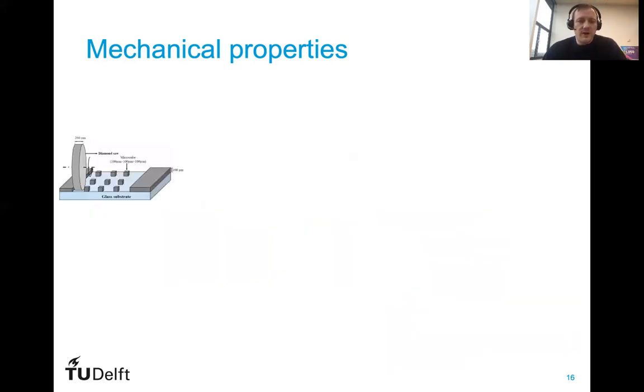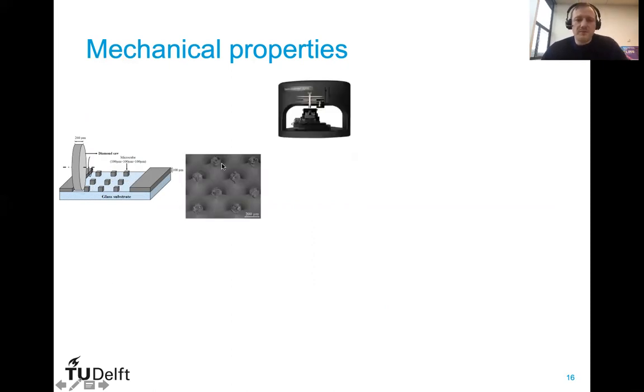So in Delft, we developed a technique for creating very small specimens, a so-called microdicing technique. We make a thin specimen, sort of a thin section of 100 micrometer thickness, that we dice in 2 directions, and then create an array of microbeams. These beams can then be tested. So this is how they look under an electron microscope. And we test them using a nanoindenter.